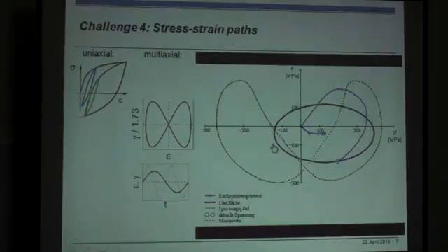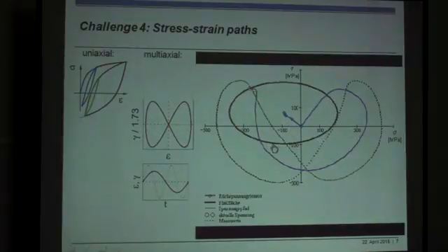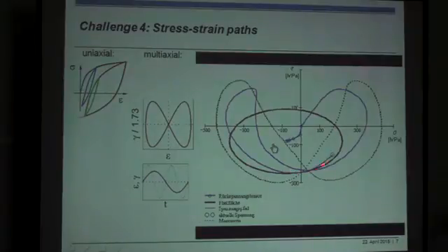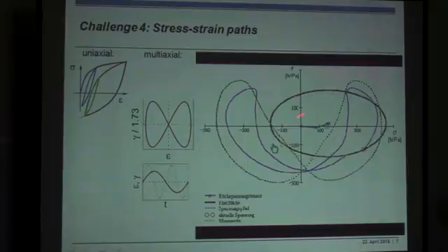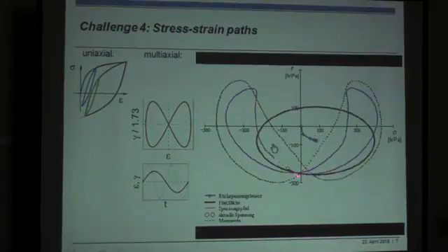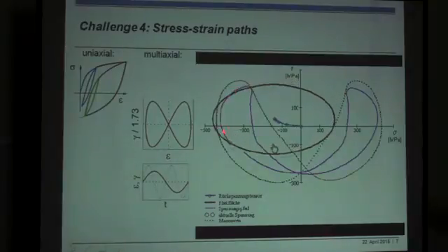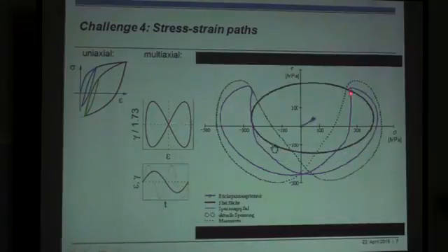Integrating all this equational stuff finally ends up in such a path. Here, this is the actual path calculated, going up, here and down. Here you see these backstress tensors. We used 5 backstress tensors. You see under these butterfly path conditions, as long as a point is on the yield surface, you have plastic deformation.